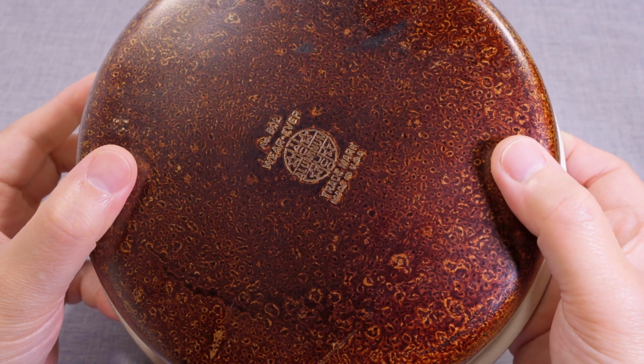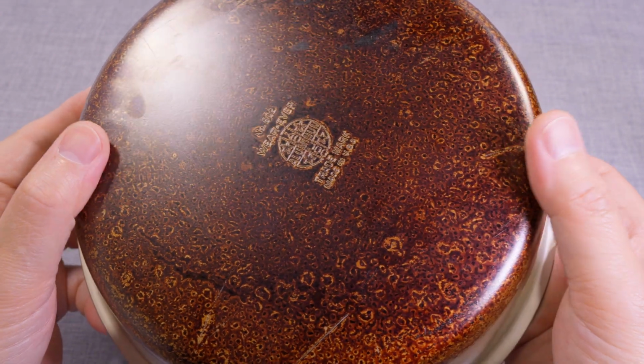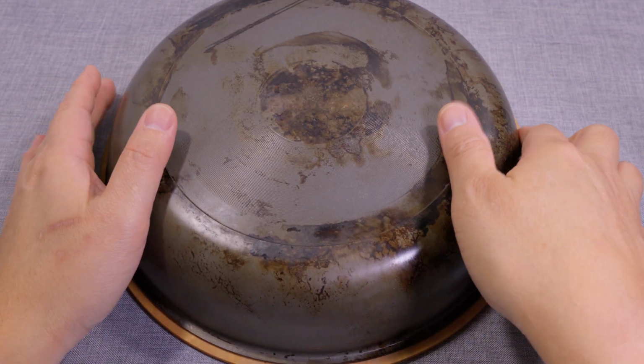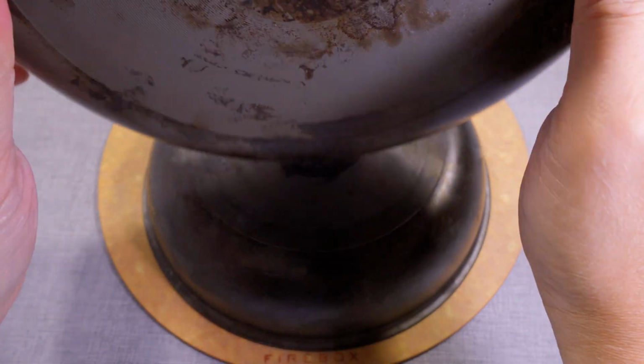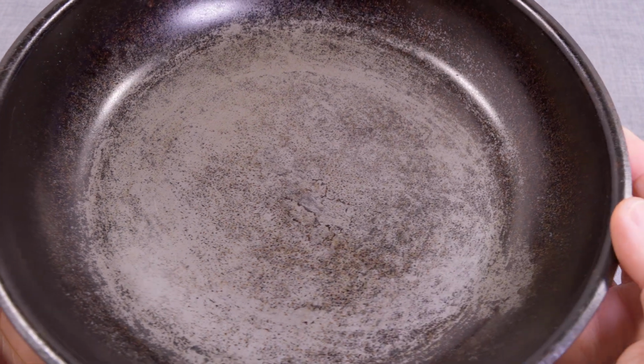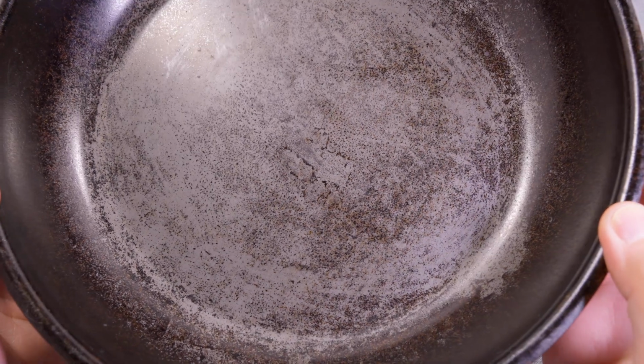This was enough evidence for me to strip my 10-inch pan down to the anodized aluminum and test grapeseed oil. I used the same process, but only did it for an hour for that last and final layer. I can tell you that it looked beautiful. I made some bacon on the stovetop, and it worked flawlessly until it came time to cleaning. I collected all the bacon grease and let it cool naturally before I cleaned it. I ran hot water over it and used a soft sponge with no soap to get the stuck bacon bits off the bottom. The seasoning just washed right off with little effort.